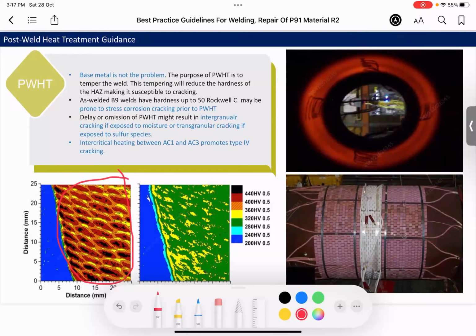So without tempering, as I said, it may be prone to stress corrosion cracking prior to PWHT, and the delay or omission of PWHT might result in intergranular cracking if exposed to moisture, and transgranular cracking if exposed to sulfur species. And intercritical heating between AC1 and AC3 promotes type IV cracking or cracking in the heat affected zone.